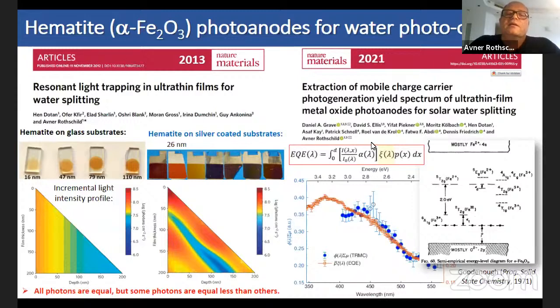And we recently published, about 2 weeks ago, an article that shows 2 methods for extracting this material property. And it shows that about 40% of the photons are lost. And that explains why we cannot get the 12.6 milliamps, but only less than half of the theoretical limit for this material. So with this, we learned that all photons are equal, but some photons are more equal than others.